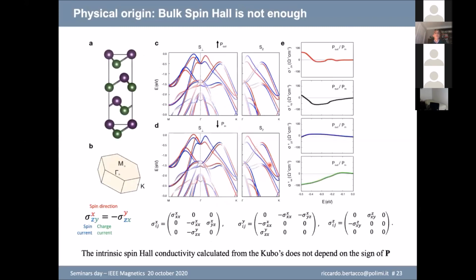And what about the physical origin? Without entering into the details of the calculation, because I'm running out of time, Marco Nardelli performed some calculations just to see if bulk spin-Hall can explain what we are seeing, and the answer is no, simply because when you revert the polarization, nothing changes. When you calculate the spin-Hall conductivity, it is totally unchanged. As you can see here, for P out and P in, you have the same elements of the tensor.